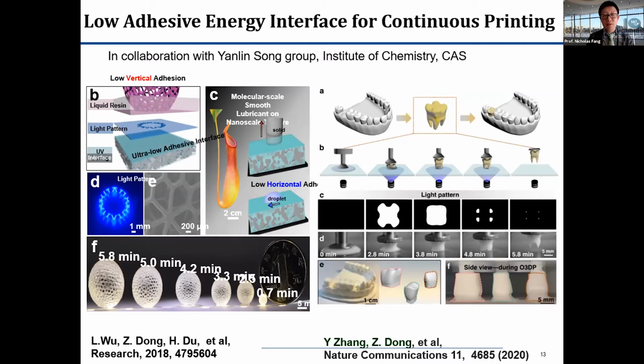So here, in collaboration with Professor Yanlin Song's group at the Institute of Chemistry, we are able to minimize the surface adhesion between the, say, spreading of different liquid layers. And by doing so, we can now really generate a ping pong ball size of, for example, these Buckyball structures in the order of a few minutes. And similarly, we can now also minimize the use of some of the expensive, I'll say, functional materials, say, for ceramic resins. Some of those compounds are actually hundreds of dollars per gram. So we have to really now minimize their waste. Here we see that such improved surface lubrication also gives us a new avenue to achieve that goal.